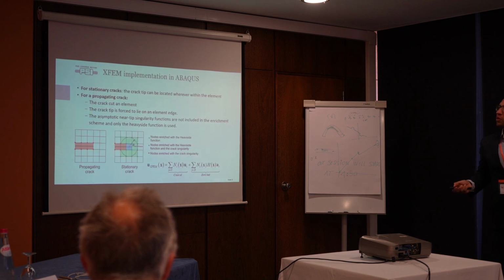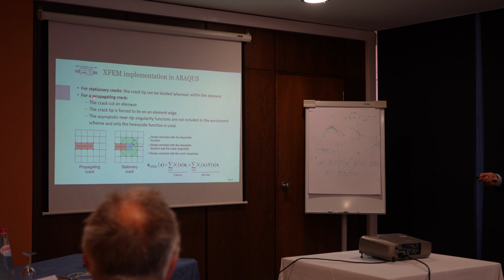So this slide just briefly describes the implementation of XFEM in Abaqus. Here in Abaqus you can use XFEM for stationary cracks, in which the crack can be located wherever in the element, like it's shown in this diagram, and it accounts for the full enrichment.